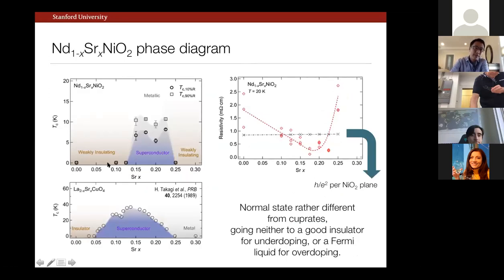So to show this in phase diagram form, here's the nickelate phase diagram we deduce. These zeros are statements that, at least down to the base temperature of our dilution fridge, we see no signs of the onset or the proximity of superconductivity, and we see a narrow dome, okay, in this range. And just to give you a point of comparison, this is what you see in the 214 cuprates for hole doping. Okay. So tantalizingly similar in approximate position and qualitatively. It's quite a bit narrower. It's actually more similar to what you find in the electron doped 214 cuprates. But the thing I want to emphasize again here is this rather strange normal state on either side of the dome.